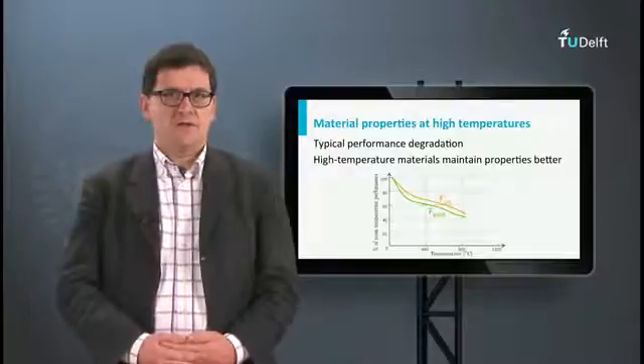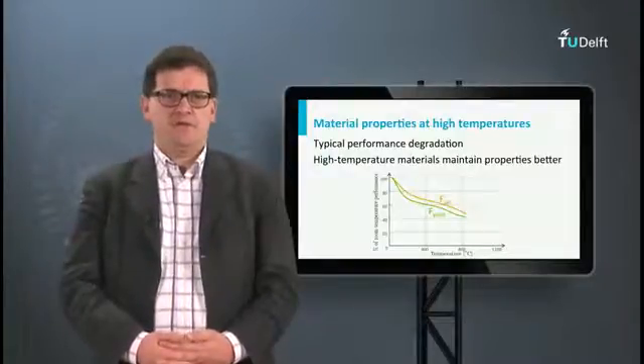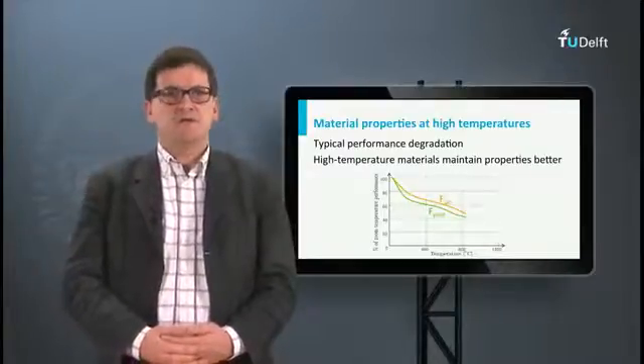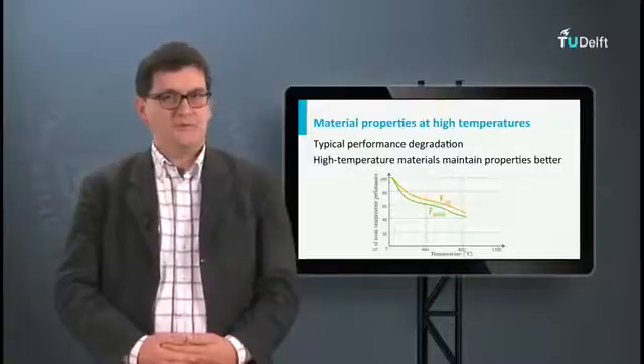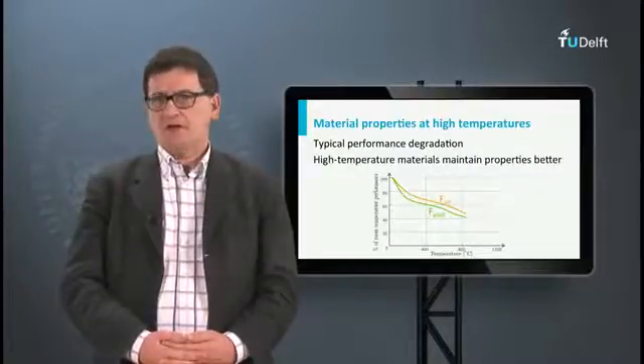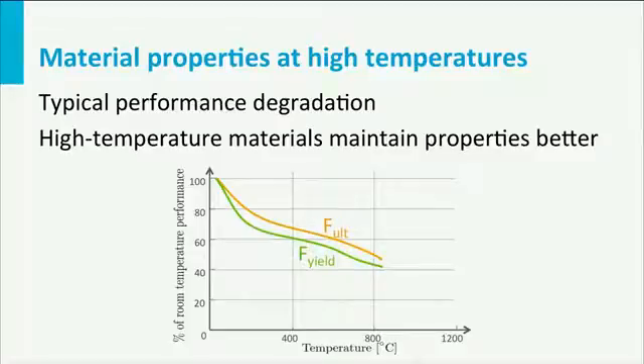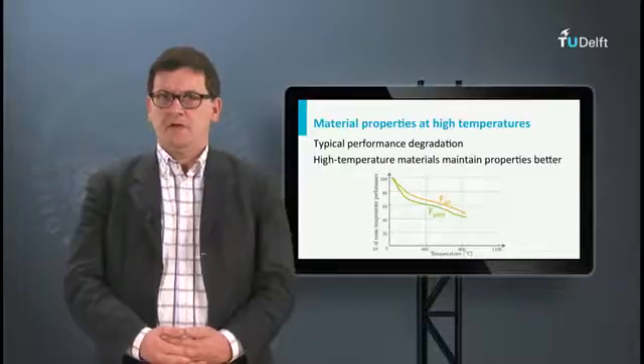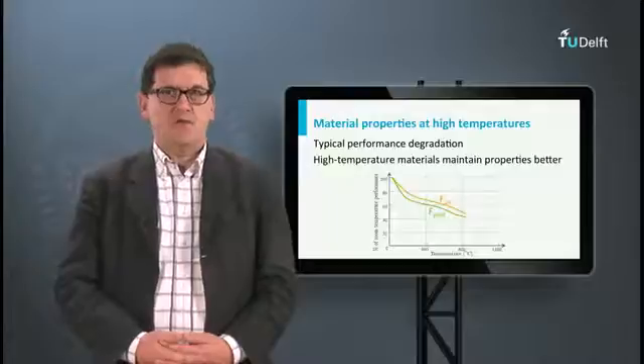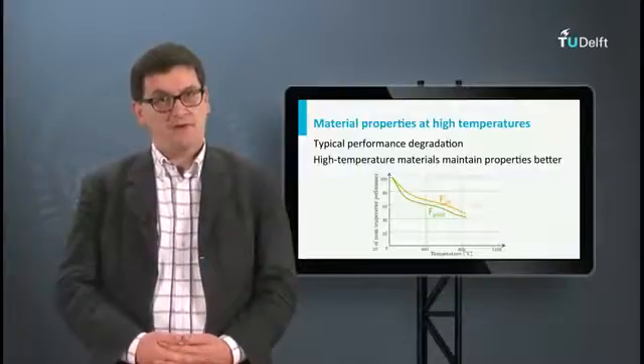steel alloys. In this respect, titanium is favorable because of its low density, which is 4,500 kilos per cubic meter. This is much lower than for the steel alloys. In this picture, you see the relative values for the ultimate strength and the yield strength of a titanium alloy as function of the temperature. Reading from this plot, we can see that there is a significant drop in values at about 150 degrees Celsius. After that initial drop, the properties decrease slowly. At, for example, 500 degrees Celsius, still more than 50% of the room temperature property values remain.